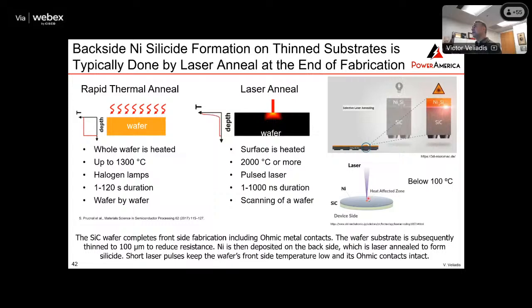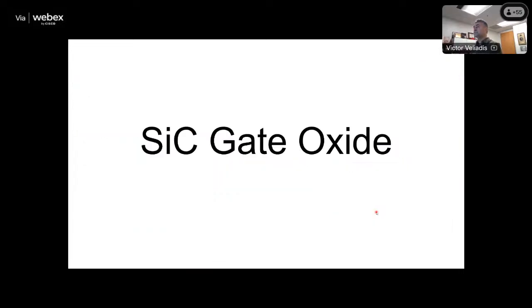And the reason why you use this laser anneal is because the wafer is now thin, the whole front surface is fully processed, and if you put it in a rapid thermal annealing, you will basically melt the ohmic contacts on the front side. If you use the laser anneal in the back, you're going to raise the temperature locally, but the front of the wafer will be below 100 degrees, which is not a problem.